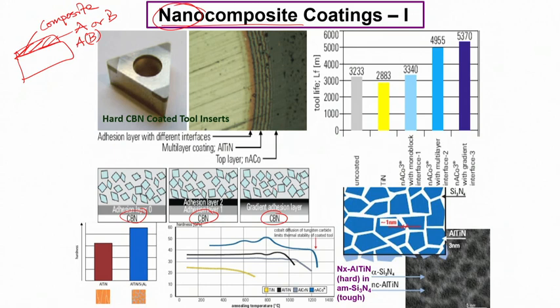Surprisingly, in this case, the softer binder is actually an amorphous material, silicon nitride, not in crystalline form but in amorphous form. So the harder phases are actually a mixed nitride, aluminum titanium nitride, in nanometric form. So these nanometric nitrides of aluminum titanium nitride are dispersed in this amorphous layer, which is a silicon nitride. Now stoichiometrically this may not be exactly Si3N4, but somewhat similar.